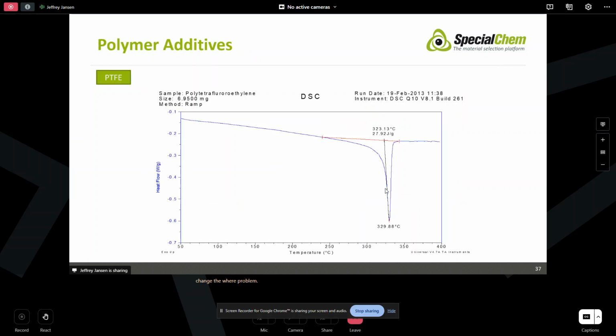So if we look at a sample of pure PTFE, we can understand the heat of fusion of that material. That's, again, 100% pure. This is the second heating run, and we're going to talk about that a little bit later. But this is the second heating run, which allows our material to be optimized for crystalline state. And we see that we've got about 28 joules per gram. That's the energy required to melt that material at 100% pure.